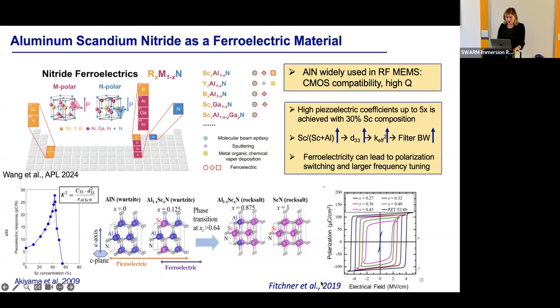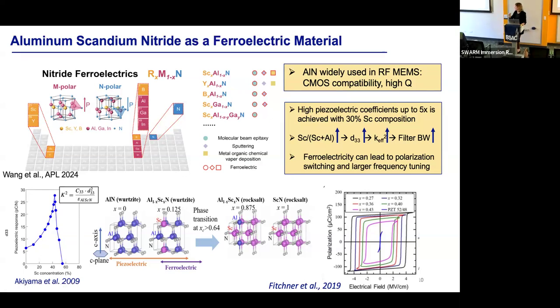Now, more recently in 2019, for the first time, it was shown that you can actually switch the polarization of aluminum scandium nitride, let's say from metal polar to nitrogen polar. This was very important, basically, to see these very nice box-like polarization versus electric field profiles, which adds switching capability to your otherwise purely piezoelectric material.